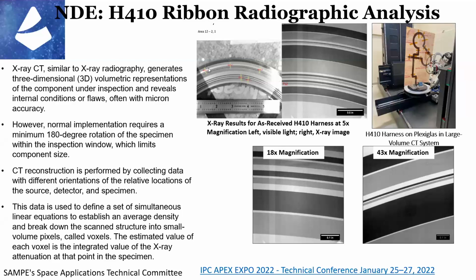So anyway, one of the things that we did notice in the harness was that some of the traces were a little bit darker in X-ray than the others, but initially it didn't seem to really be something of interest until we went just a little higher, and now we can certainly see some big variations in the wires and where they're located. This is our large area CT system that we have here at Langley.